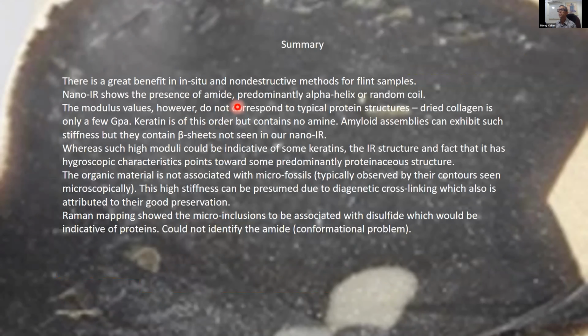Just to summarize that, and I'll get back to that, I would like to say that we did show that using this technique, we can locate a specific region on the surface, analyze them chemically and mechanically, and correlate their behavior. The nano-IR shows us that we have an amide, which is predominantly in the alpha helix or the random coil. But if we look at the modulus values that we might expect to see when we have amides or proteins, they don't look like proteins, because something like collagen or other common proteins have a modulus which is about an order of magnitude lower than what we measured.